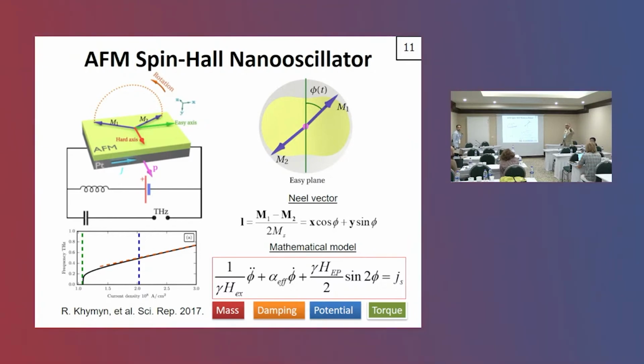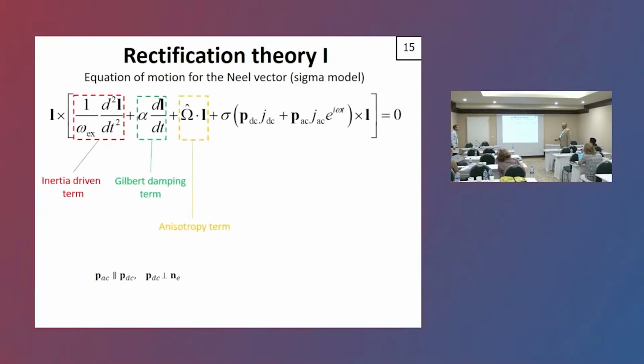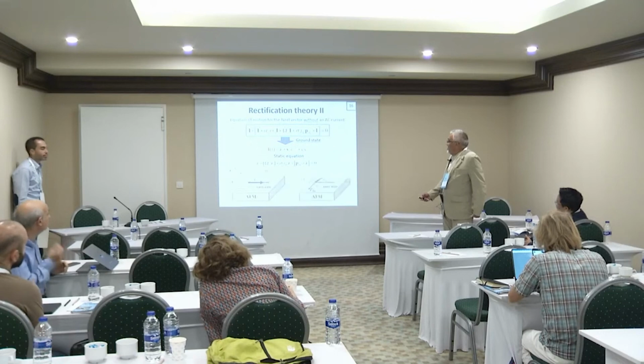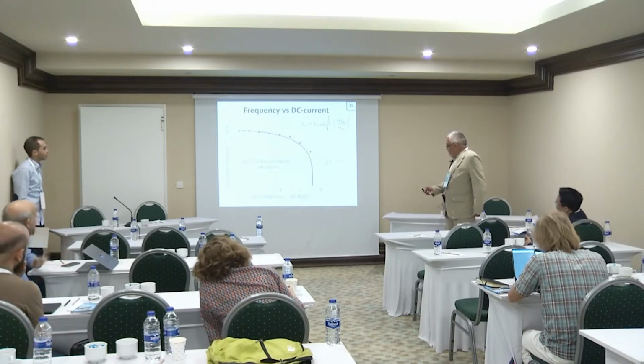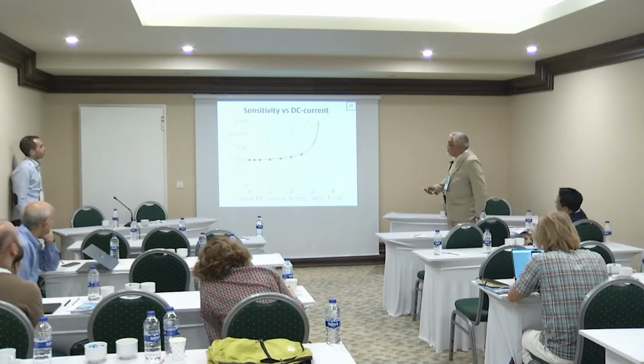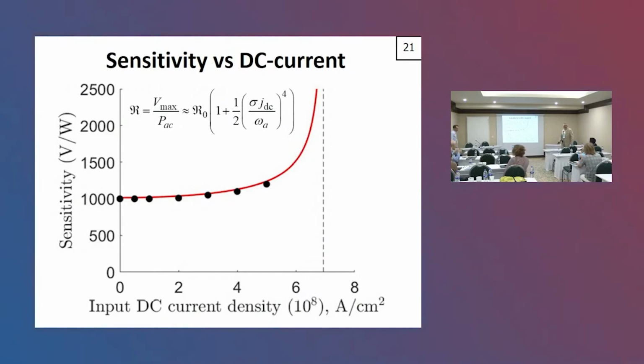Vincent wants to ask. In your final slide, you say that to increase the sensitivity, you can insert a magnetic tunnel junction. But then, if I'm not wrong, you have platinum as a second electrode. With sensitivity as in a detector, you see the sensitivity depends. We assumed that the thickness of the antiferromagnet is rather small, 30, 40 nanometers, not more than that. In that case, you can get a good sensitivity, comparable to the sensitivity of GaN diodes or Schottky diodes. So there are no miracles here.